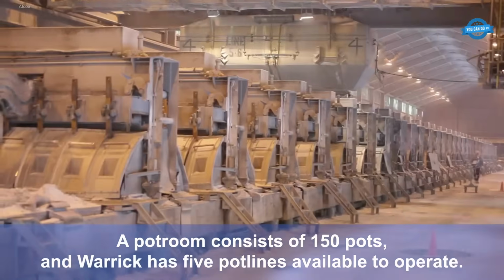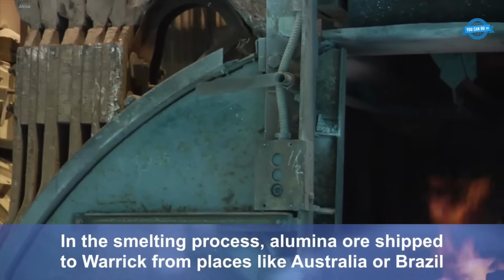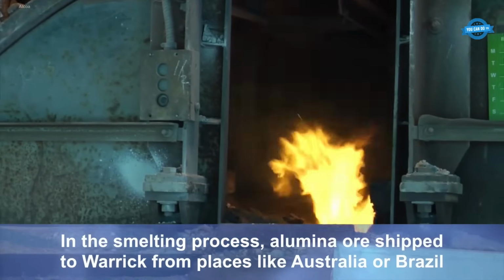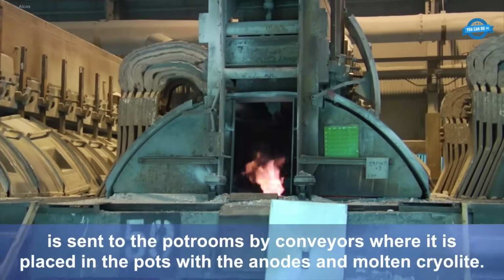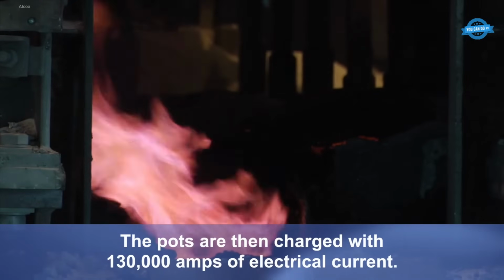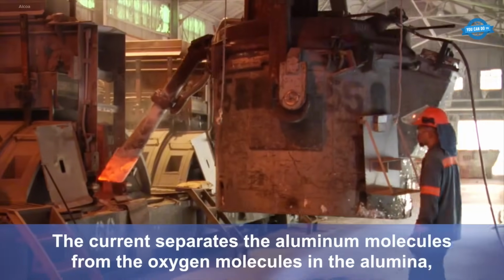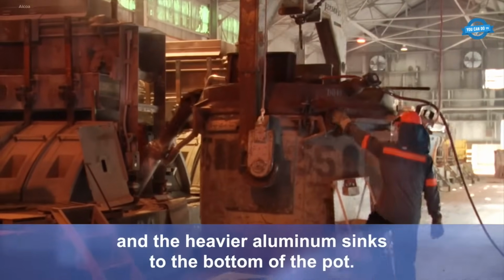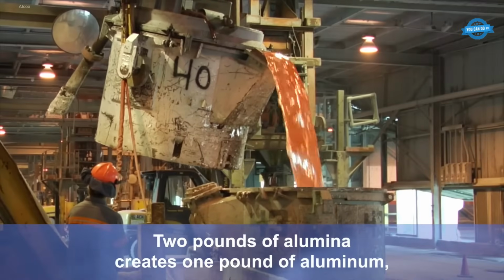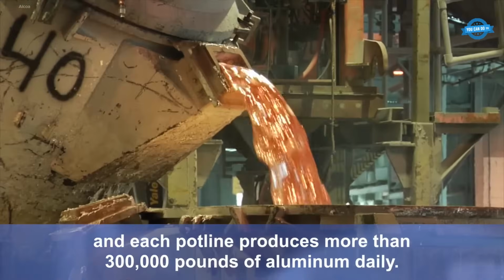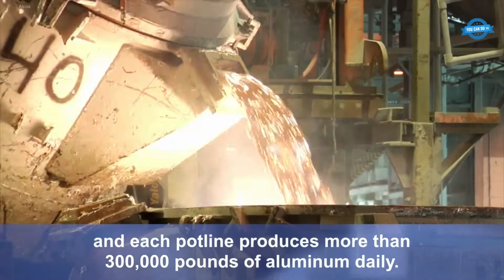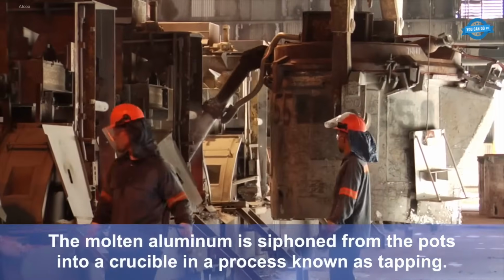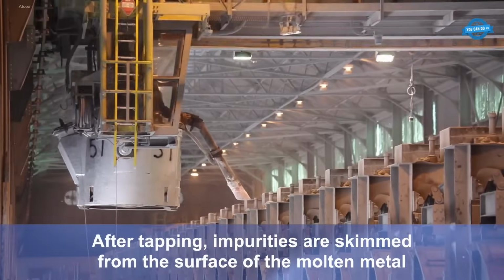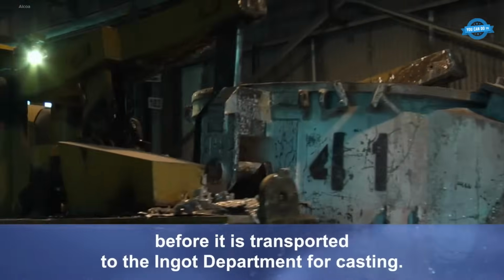Alumina, shipped from Australia or Brazil, is conveyed to pot rooms mixed with molten cryolite and charged with 130,000 amps. This separates aluminum from oxygen, with molten aluminum sinking to the pot's bottom. 2 pounds of alumina yield 1 pound of aluminum, producing over 300,000 pounds daily per pot line. The molten aluminum is siphoned into crucibles via tapping, impurities are skimmed, and it's transported to the ingot department for